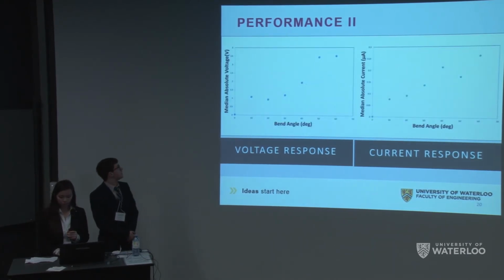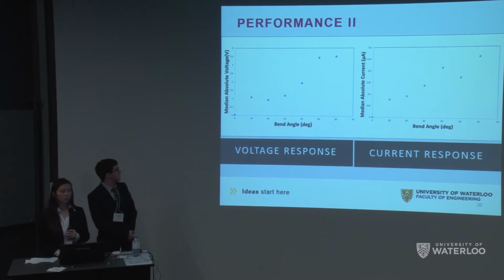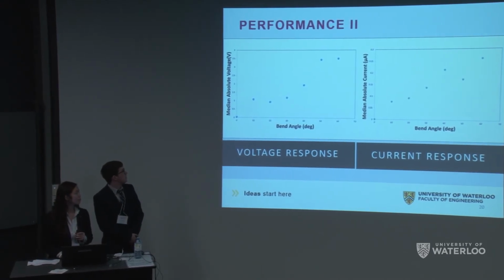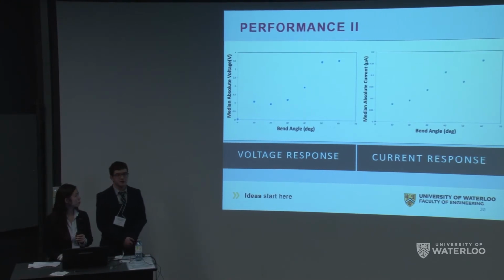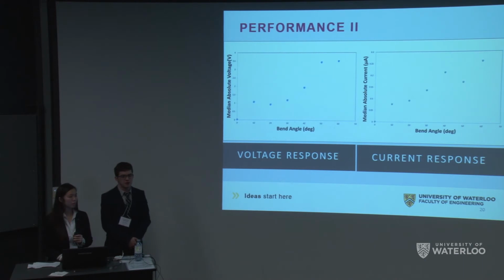So we measured the median absolute voltage and current as a function of bend angle. First, as you can see, there is a fairly clear linear trend. And when we used the 60-degree angle of bending, we found a power output of 0.52 microwatts. However, when we used our max bending, which is close to 180 degrees, a little bit under, we found a power output of 6.77 microwatts, which met our customer requirement.